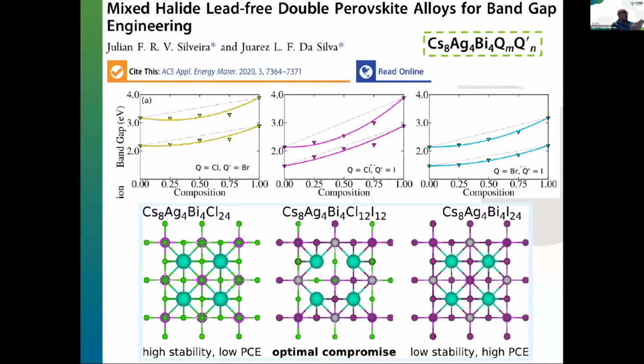But the band gap is so high, the power conversion efficiency will be lower. But if you go in the direction of iodine, we have a low stability, but higher power conversion efficiency because of the good band gap. And then you have a compromise that we suggested, a mix of chlorine with iodine. Okay, we can take the advantage of improving stability, but at the same time compromise in the electronic properties. And then we move on.